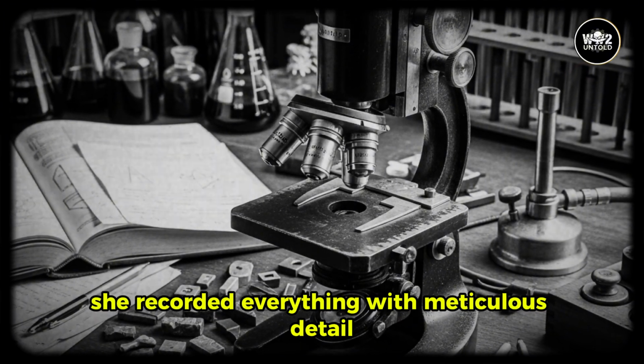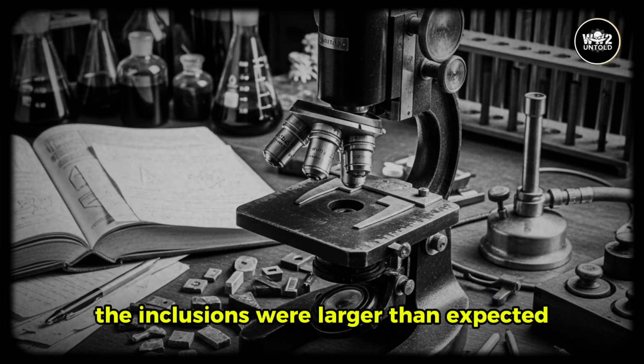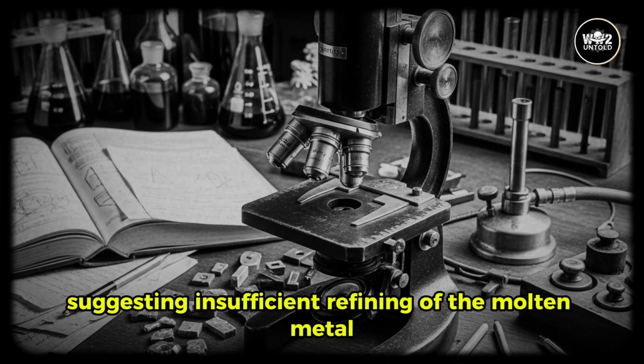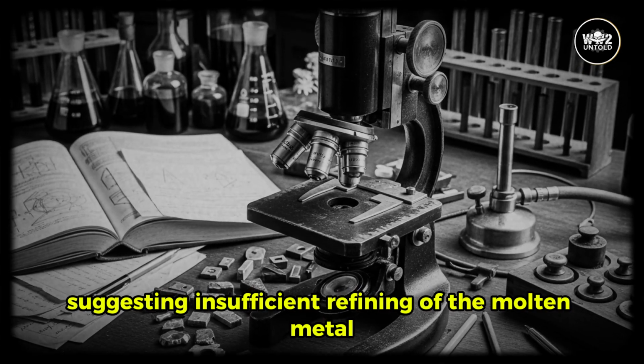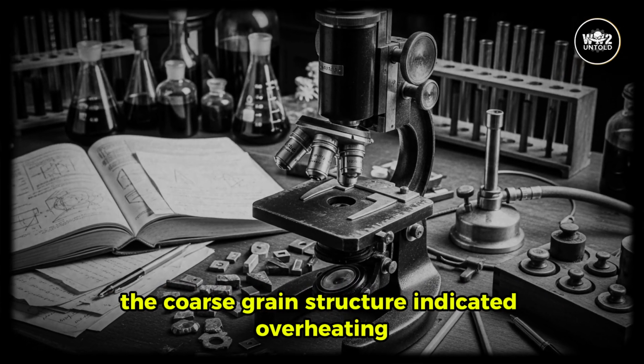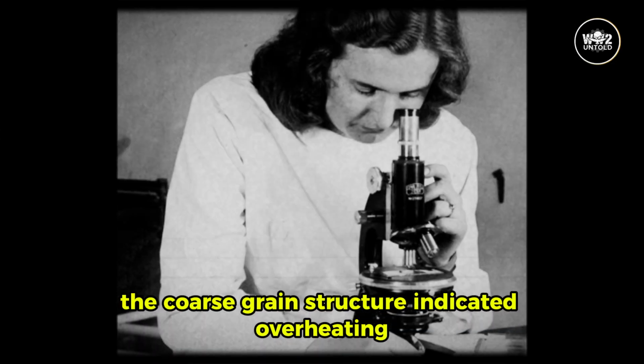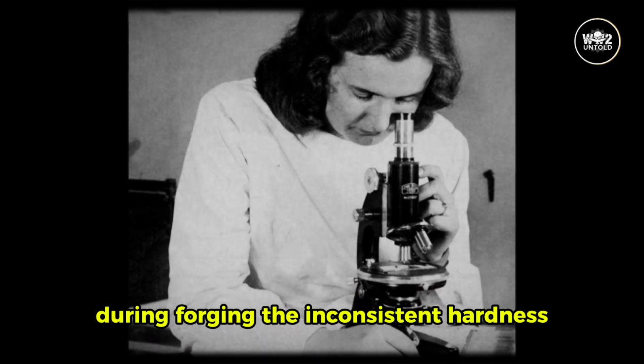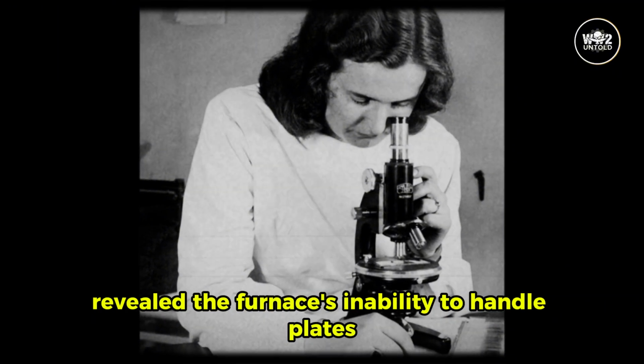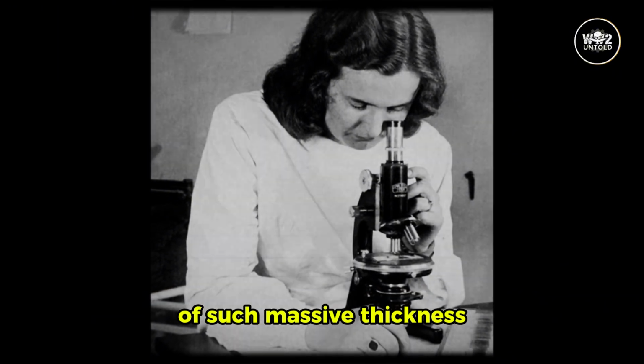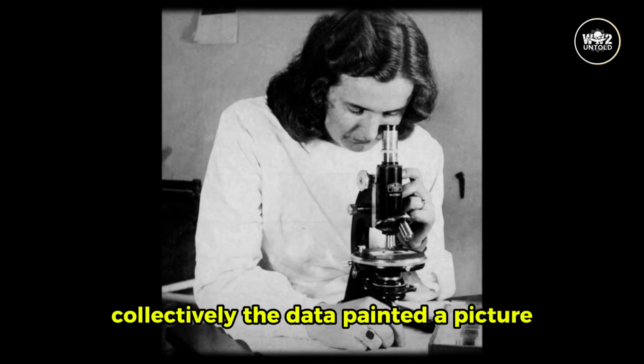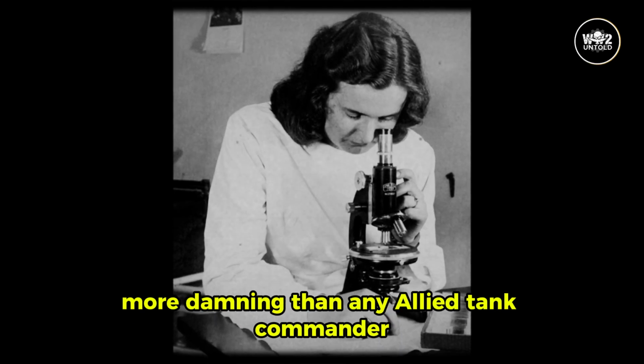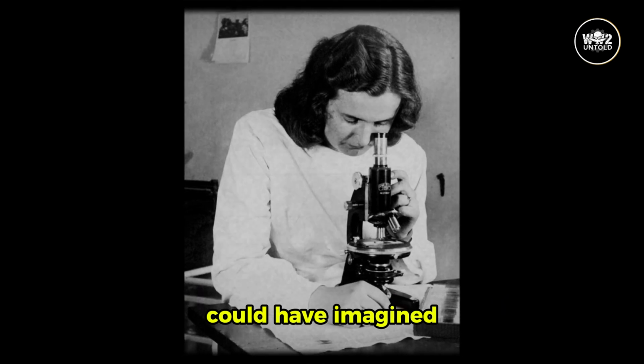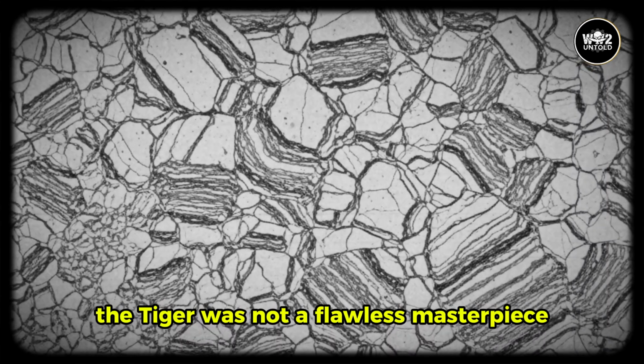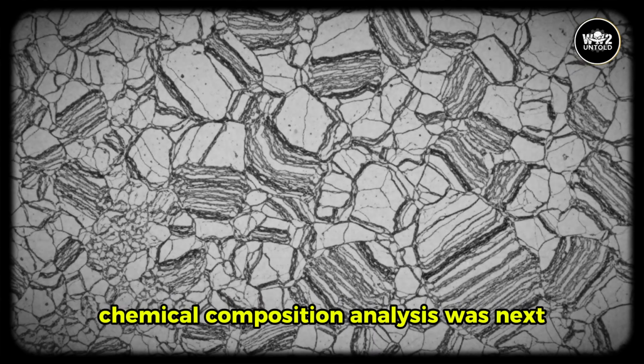She recorded everything with meticulous detail. The inclusions were larger than expected, suggesting insufficient refining of the molten metal. The coarse grain structure indicated overheating during forging. The inconsistent hardness revealed the furnace's inability to handle plates of such massive thickness. Collectively, the data painted a picture more damning than any Allied tank commander could have imagined. The Tiger was not a flawless masterpiece. It was a compromise.